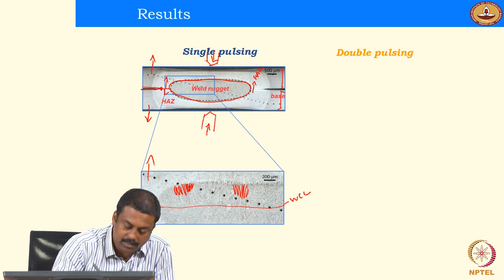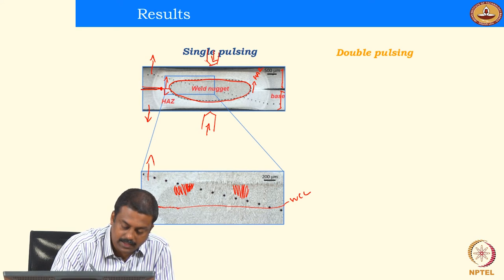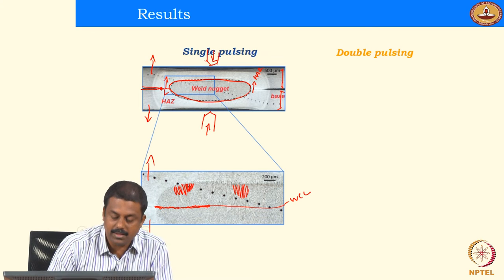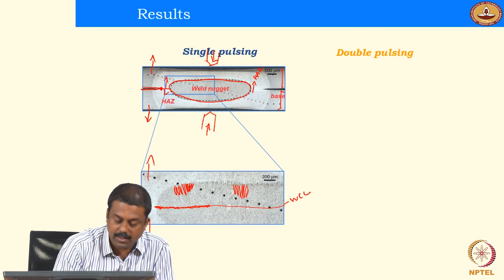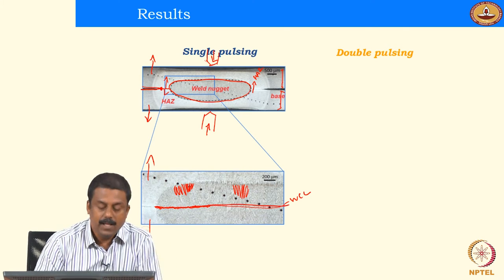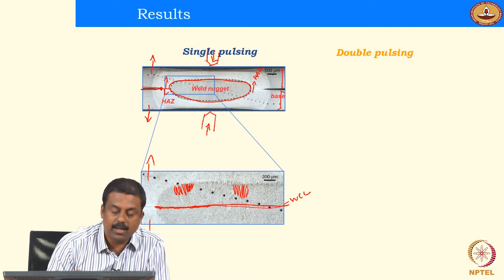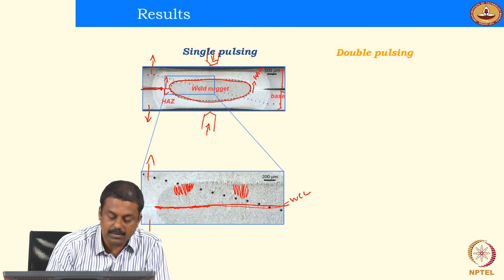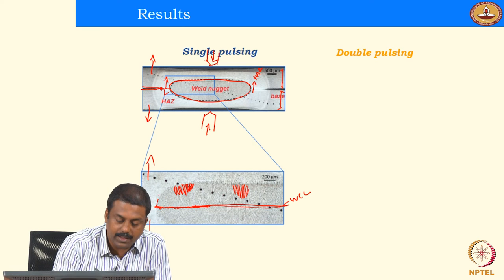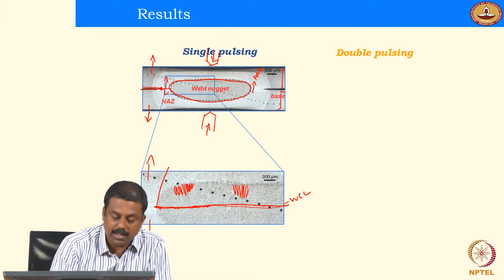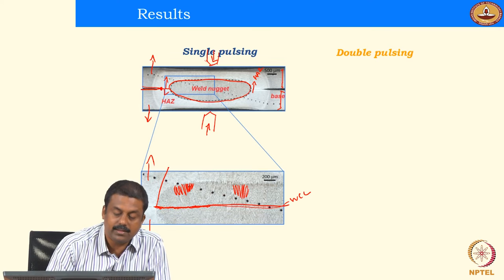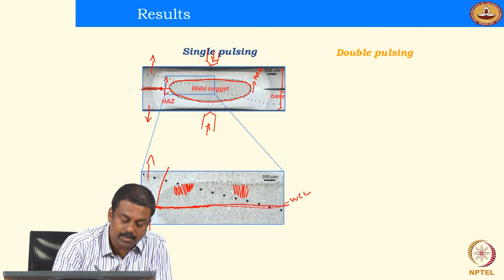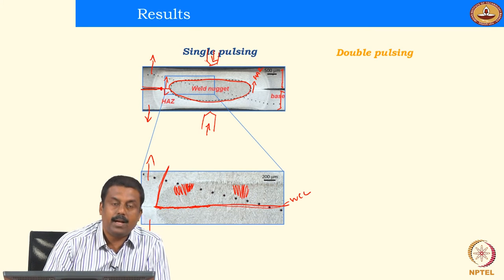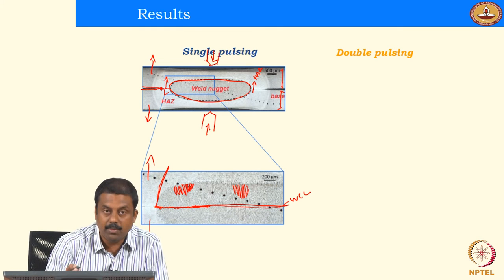And because of the brittle elements that are segregated at the weld center line, you will have crack propagation, and if you have a high amount of segregation, you will have a complete interface failure. So if the segregation is minimal, or if you do not have any detrimental element like carbon, phosphorus, then you may end up having cracks going like this, because the microstructure over here is very strong, right? This is martensitic microstructure, and you will end up fracturing at the heat affected zone. That is very good, okay.